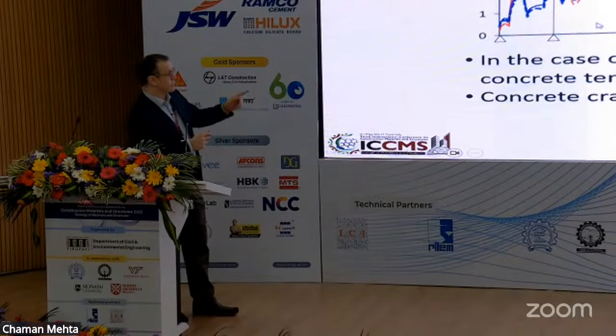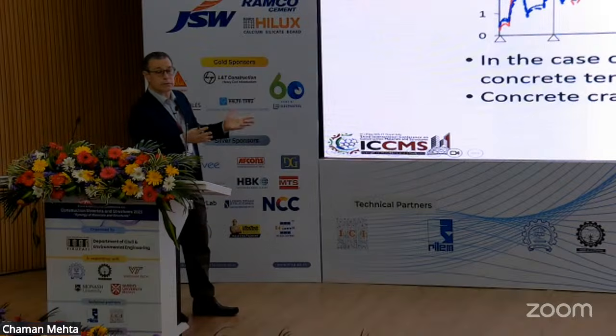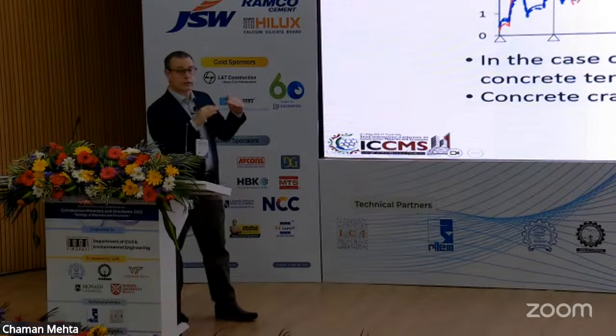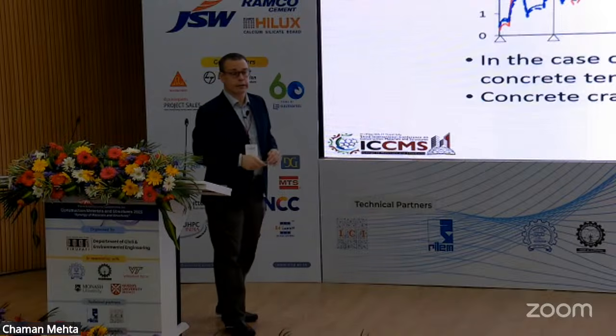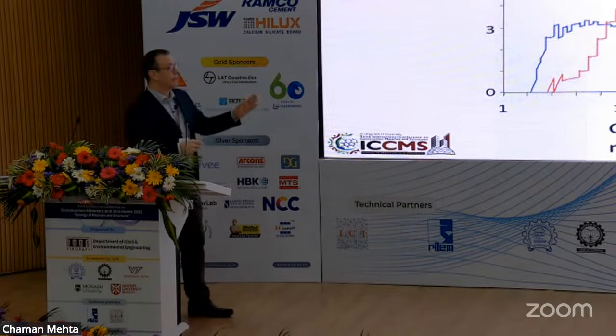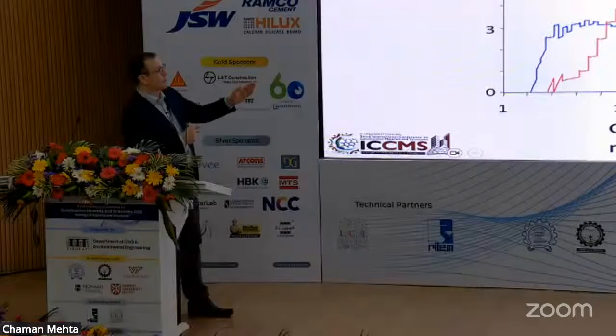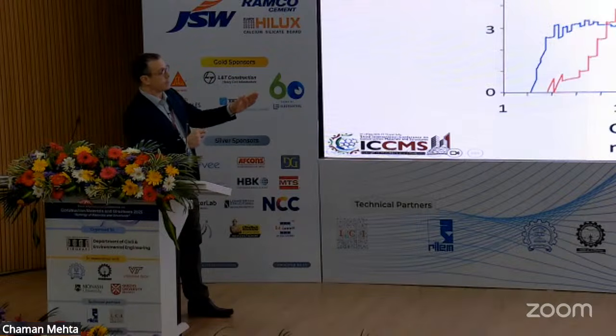The main advantages, and this is now for the bridge you saw before, is that you're pushing the peak stresses on the concrete near the second moment regions, which is fine from a modeling point of view. And you're getting away from the stresses you would have in the bridge. These are plots without traffic loads. These are just really looking at the shrinkage effects. And again, you can see at the supports you have a big difference. The red is the continuous cast, and the support is really where the issue is.